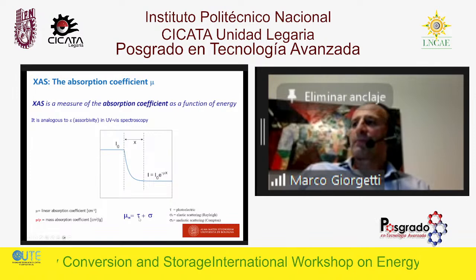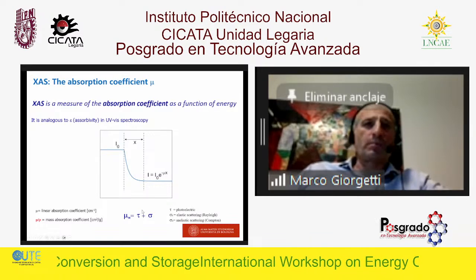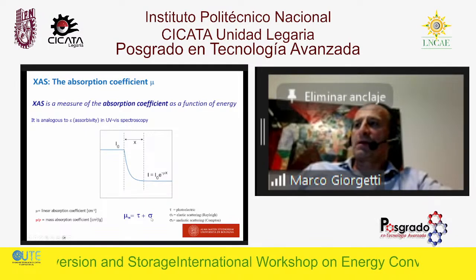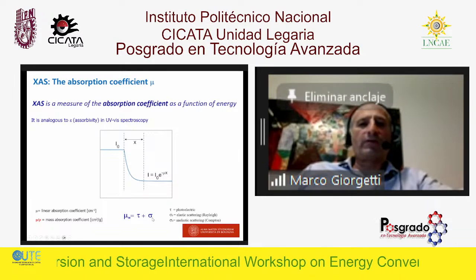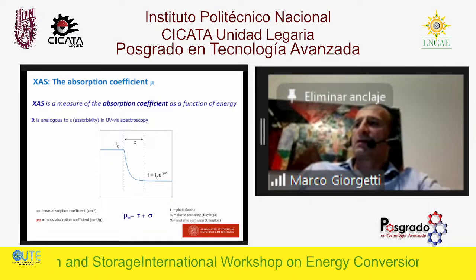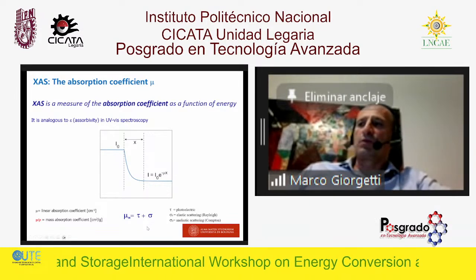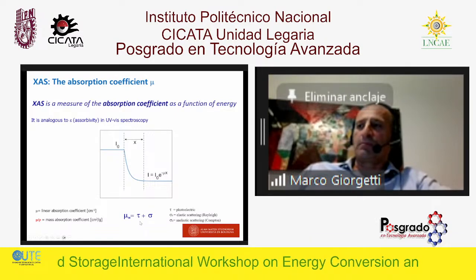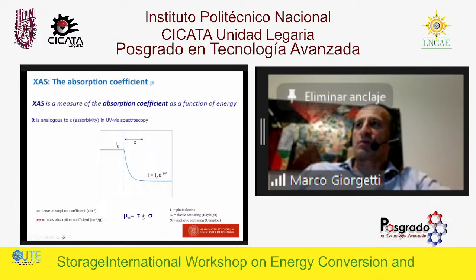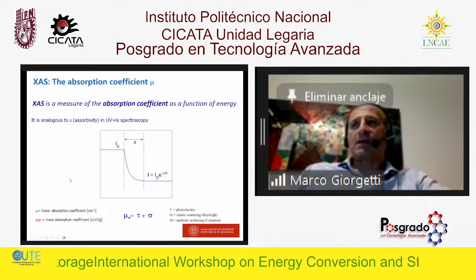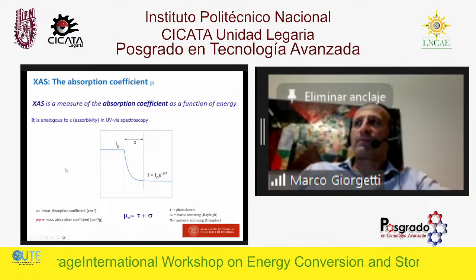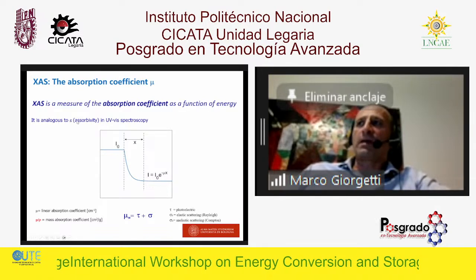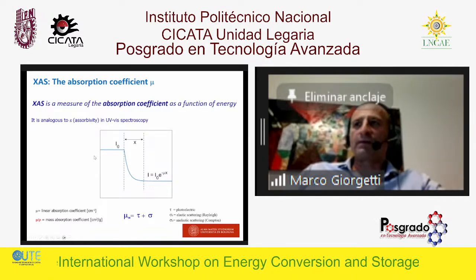One is the main and the most important one, because this is related to the absorption process that I first described, the creation of the core hole, plus you have the scattering that could be inelastic. But let's say, for all the first transition metals, which are very interesting for us, the most contributing one is just the photoelectric portion of the mass absorption coefficient. So, that said, what is XAS? XAS is basically a measure of the absorption coefficient as a function of the energy.